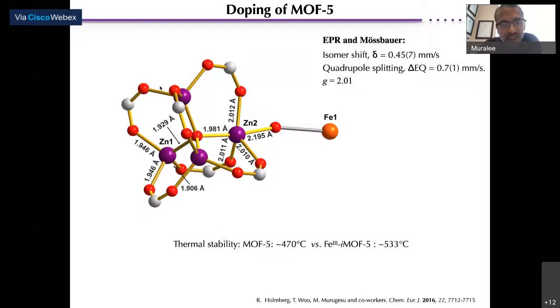If you look carefully at the tetrahedral unit of the MOF5, the new one we call IMOF5, basically you have the same zinc-4 unit, but one of the zincs, instead of adopting a tetrahedral environment, is now adopting an almost square-based pyramidal geometry, where one of the oxygen atoms is linking the iron center. Of course, we have tried several X-ray diffraction data sets, including even synchrotron diffraction. What we found is that this electron density is quite clear. We can also see these ones, but